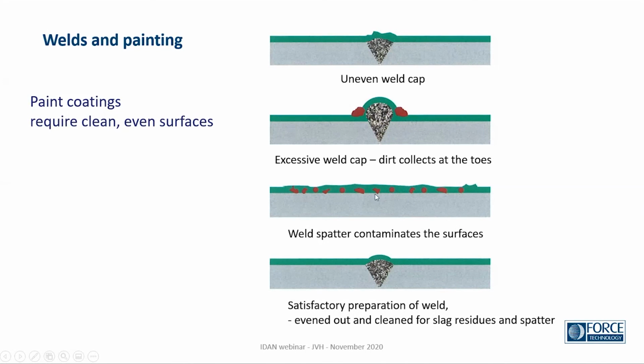Worse if you have contaminants or weld spatter or whatever slag on the surface below the paint, then the effective thickness of the paint is very poor in some of these points, and you could get corrosion problems. So a smooth weld, clean from any spatter or slag or other residues or contamination, that's the best way to get a good protection from paint.